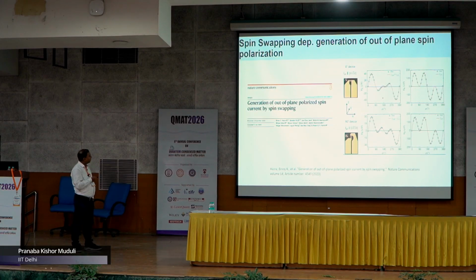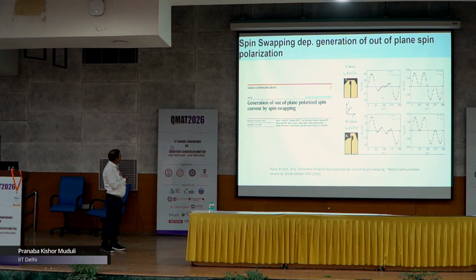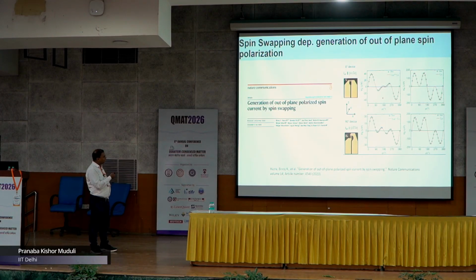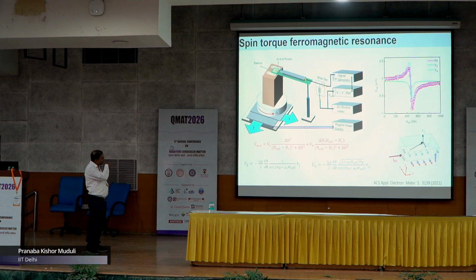If you look at this paper here, they were just doing spin torque ferromagnetic resonance, and they mentioned that the out of plane spin current that is generated is not due to the magnetic spin-Hall effect, but due to the spin swapping effect. This is a new effect that arises only from the interface, so it has nothing to do with the magnetic structure of Mn3Ir. This appears to contradict the previous paper that claimed the magnetic spin-Hall effect. So there is an apparent contradiction between the mechanisms of generation of the out of plane spin current in Mn3Ir. That is why we wanted to investigate.